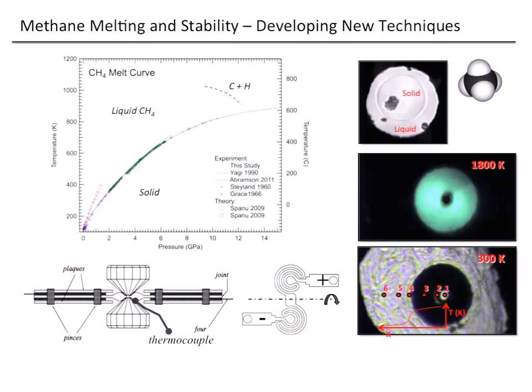One of the big problems in laser-heated diamond anvil cell experiments is that you tend to have large temperature gradients, and unless you really know what part of your sample you're probing, you're probably not at your temperature maximum, or you're at some part of this Gaussian beam profile. You also have material tending to move away from the hot spot within your sample chamber. So this is a challenging thing to do.